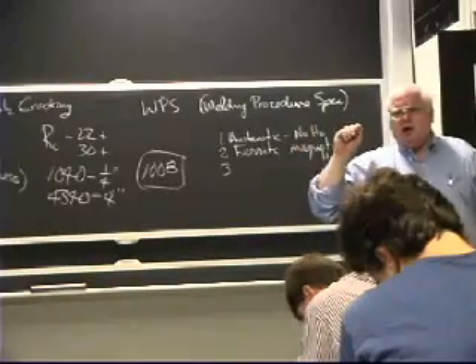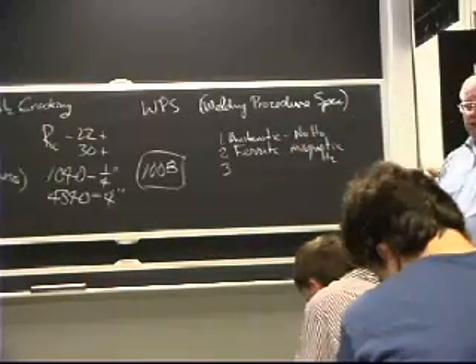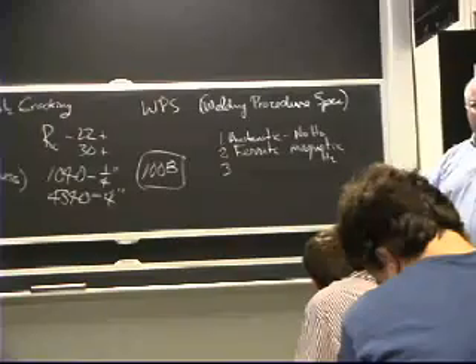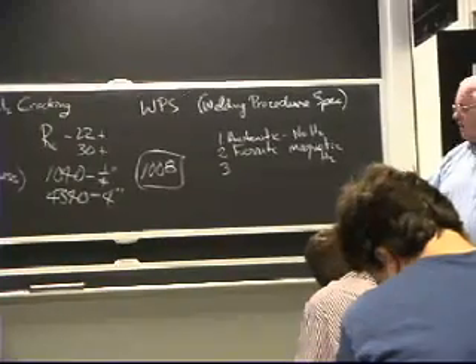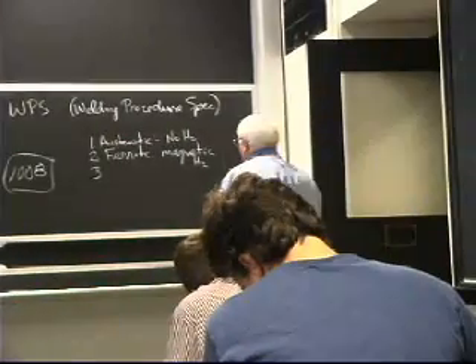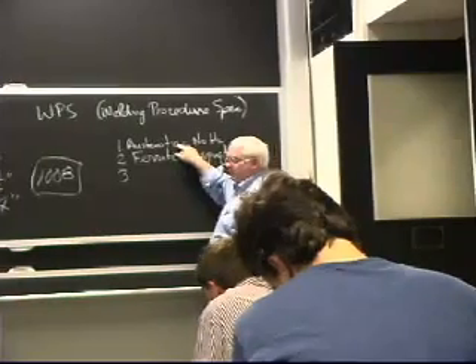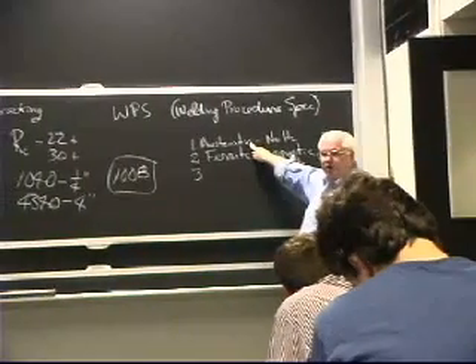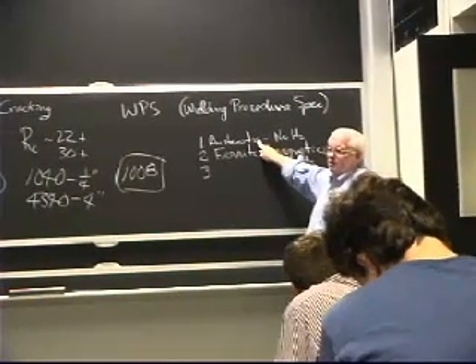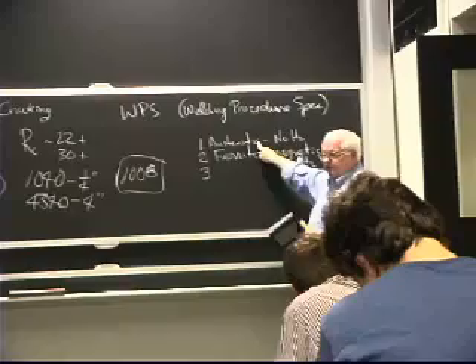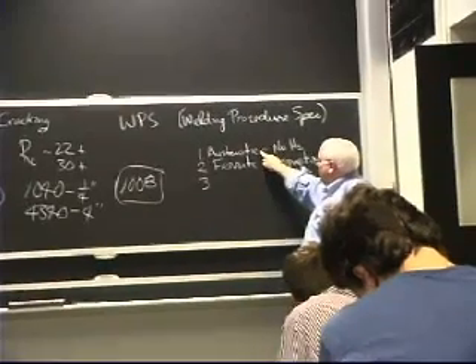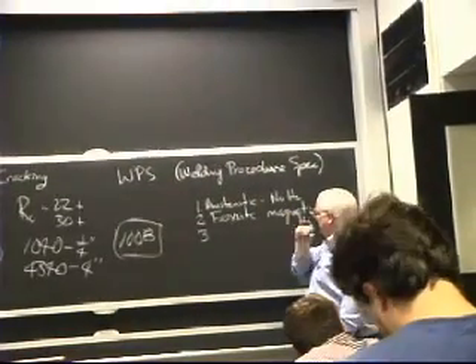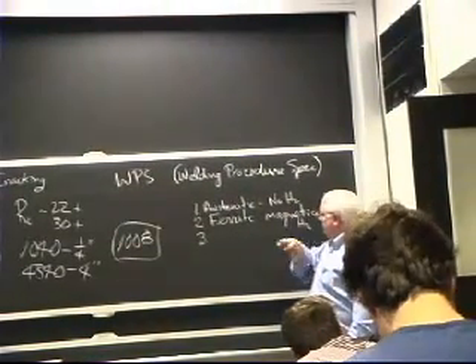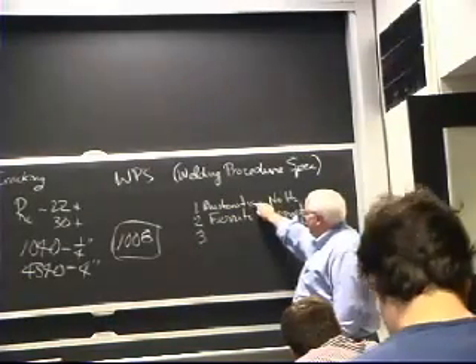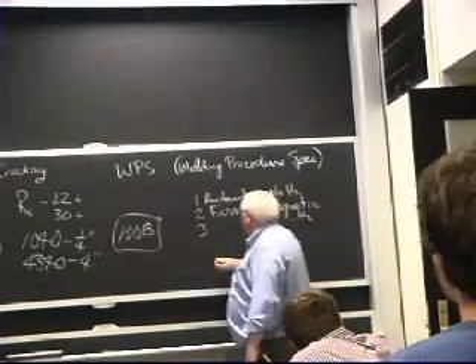Supposedly, when they first started welding the Nautilus submarine or some of the early prototypes in the 50s with higher strength steels, they couldn't solve the problem. They really just didn't have the technology at the time that we do today. And so, just to keep things on schedule, they welded with austenitic weld metal, which led to corrosion problems because you have dissimilar metals now, and also lowered the diving depth of the submarine, because these are not as strong as these. That's one of the reasons we use these.